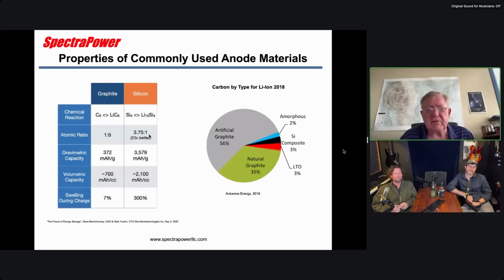But there are some problems with that as usual. So graphite gravimetric energy, just of the materials, 372 milliamp hours per gram is a typical number. But silicon, if you fully lithiate it, in other words, you pack in all the lithium you can into the silicon, you can end up with almost 10 times that capacity, which is obviously a big deal.